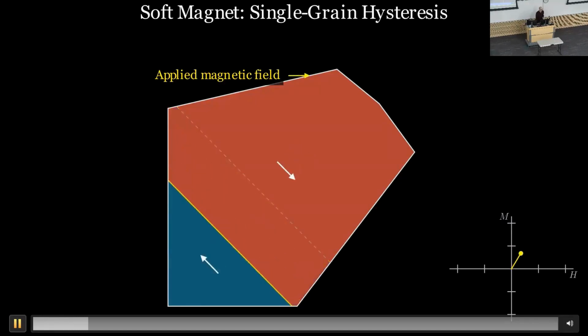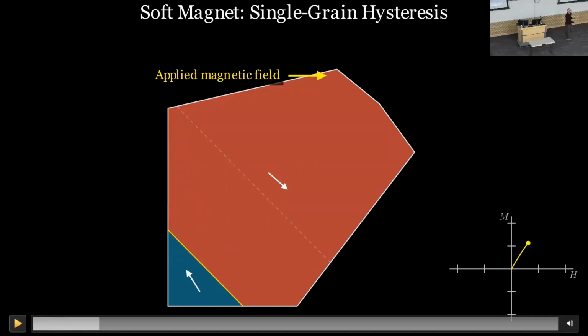As we start to apply the field, you see now that we have a yellow arrow. One of those two regions has grown at the expense of the other, and a little yellow border has started to move. That little border is called the magnetic domain wall, and it's very relevant for my research, so pay attention. Okay?